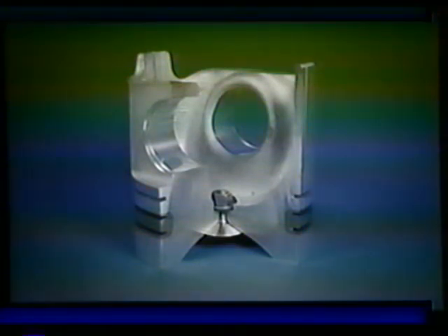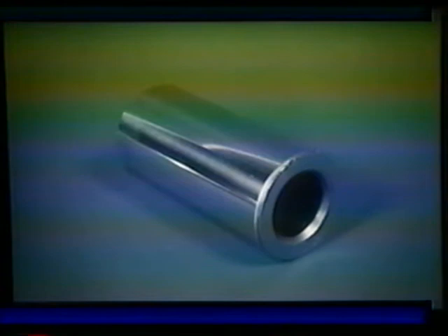To prevent cracking of the pin bore, a hard metal roller is passed several times over the core to work harden the aluminum in a process called roll burnishing. The pin bores also have a machined side relief. This pin bore side relief allows the piston pin to flex from a round to an oval shape during direction changes. The piston pin is made from a high-grade hardened steel alloy to resist deflection and breakage. It is also hollow, which allows us to reduce weight and increase fuel economy.